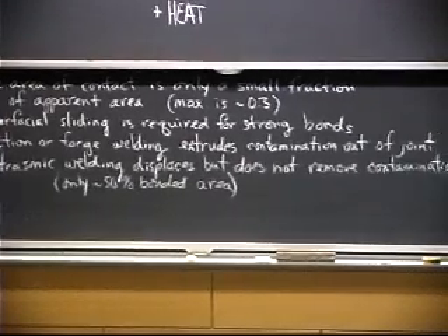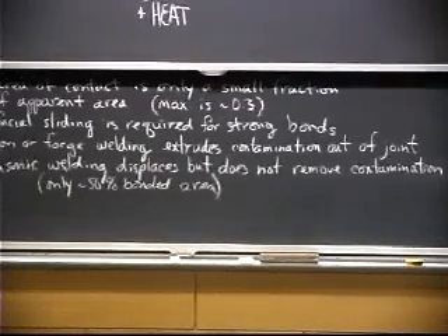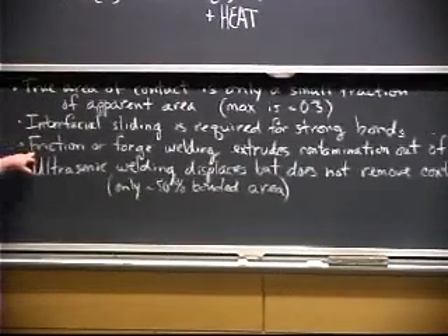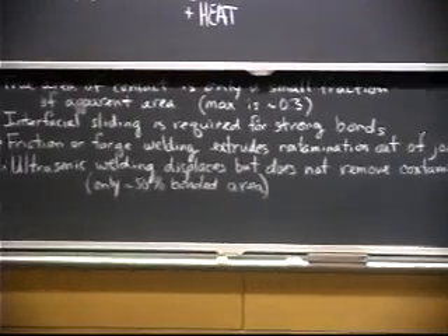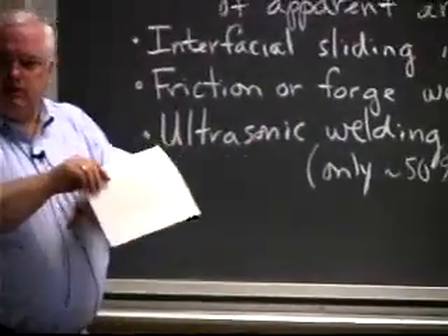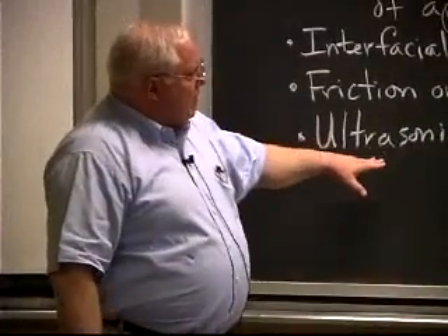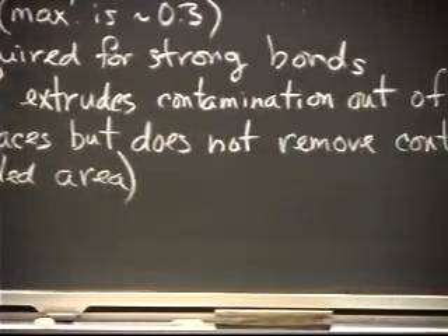Friction and forge welding, being one of the oldest types of welding, they were doing it thousands of years ago, basically extrudes the material out of the joint. You just push the contamination out of the joint. And ultrasonic welding, which is basically a micro motion, sliding motion, really doesn't get rid of the contamination. It just moves it around, and therefore you only get about 50% bonded area with ultrasonic welded joints.